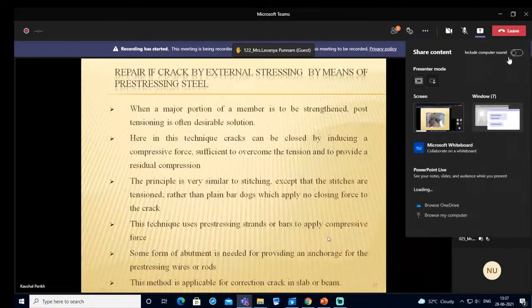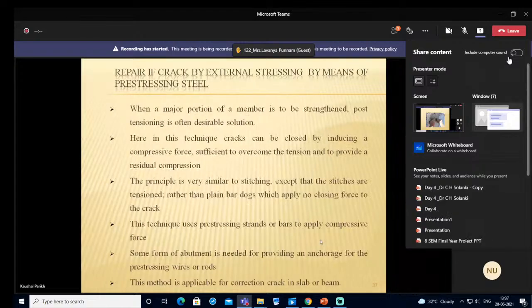I will show the stitching procedure. Now, the repairing of the crack by external stressing by means of prestressing steel. So here is the application of the prestressing steel for the repairing condition. When a major portion of a member is to be strengthened, post-tensioning is often a desirable solution. In this technique, the cracks can be closed by introducing a compressive force, because cracks are generated by the tensile force. The opposite, the compressive force, is generated by applying the prestressing steel, which is sufficient to overcome the tension and to provide a residual compression.